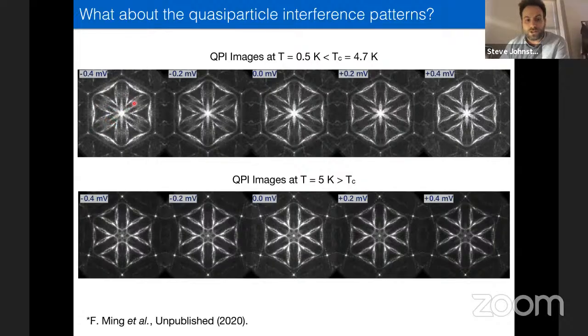What's new is this star pattern that shows up right here at the center of the Brillouin zone. And this persists all the way through the superconducting gap, whenever we're inside the coherence peaks in the bias voltages. If you warm the system up just above TC, these are dramatically suppressed, right? You can see they drop right out. There are very faint remnants of them sitting here. So this seems to indicate that these are related somehow to the superconductivity.